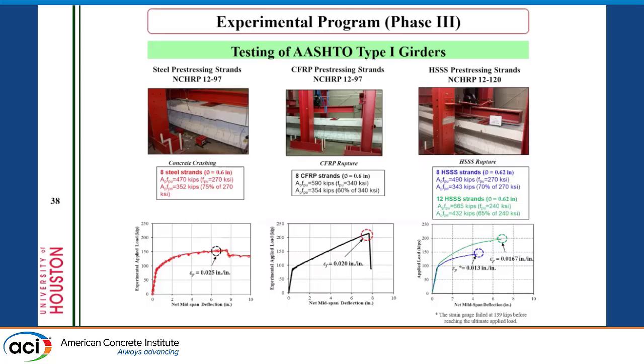So what we tried to do is design another girder so that we can get higher capacity and more deflection, because those three have the same strand, same total prestressing, and the same concrete strength. So we added about 4 strands, so they could be more or less the same.